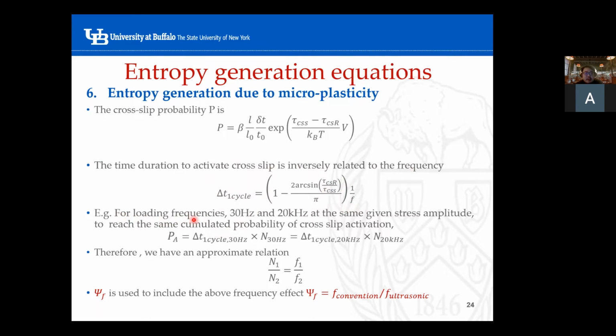For example, if we have the same stress amplitude given to the test sample, but we are operating them at different frequency ranges, one around 30 Hz, the other around 20 kHz, in order to reach the same cumulative probability of cross-slip activation, in order to make their probability the same, the time duration to activate the cross-slip per cycle times the total amount of cycles must be equivalent.